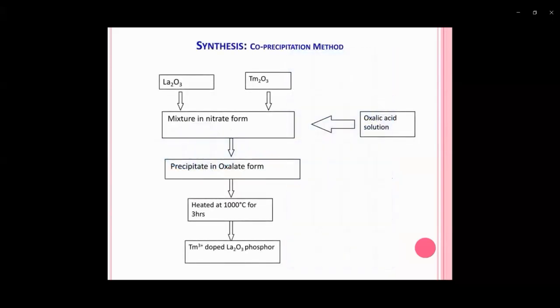Moving towards the synthesis part, the phosphor is prepared by the co-precipitation method, in which initially stoichiometric amounts of La2O3 and Tm2O3 were taken in separate beakers and then converted into nitrate form. Then both solutions were mixed in a single beaker, and a stoichiometric amount of oxalic acid solution was added to that mixture, so that the precipitate was obtained in the form of oxalate. Then the obtained precipitate was filtered, dried, and heated at 1000 degrees centigrade for 3 hours, so that Tm3+ doped La2O3 phosphor was obtained.